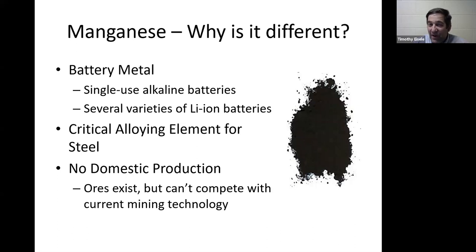Also, several of the lithium ion battery types are also largely manganese based. They are mixing the manganese with other compounds like cobalt and nickel and iron and phosphorus, but a lot of them use a significant amount of manganese. And because of this, the Department of Energy is quite interested, because more manganese availability and higher grade manganese means that it's less expensive to make batteries, and batteries are becoming a dominant part of our electricity mix.